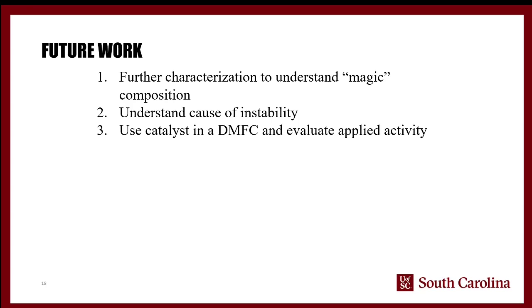And finally, what we need to do is take these catalysts, once we understand them a little bit better, and actually put them in a direct methanol fuel cell, and confirm that the small scale testing that we did translates into something closer to real life application, and check both the activity and the stability over time. Again, stability really matters, and so if it's not stable, we need to try and understand what's happening there. Is it temperature based, is it solution based, and is there anything that we can do to counteract it?